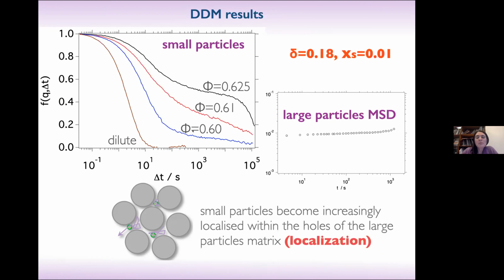You confine more and more the small particles. This is the density correlator only of the small particles, because the large ones are frozen, basically. You see that there is the onset of a two-step decay, and that it starts from 0. This is what I told you before is called the localization transition, or type A, where the plateau doesn't go directly to a high value, but starts from a very small one in a continuous way.